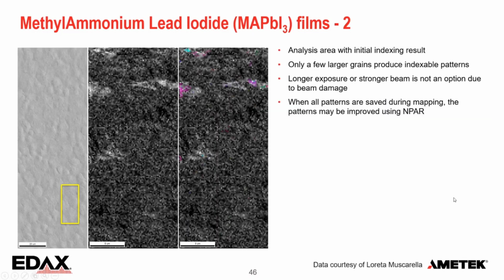And here we have a small scan on that material. In the original indexing results, this is the IQ map. And here, the brighter it is, the better the pattern. Well, it's almost all dark gray and black. There's no pattern at all. And we can get a little bit of indexing in a few of these small grains close to the top. In the rest, there's just nothing there.